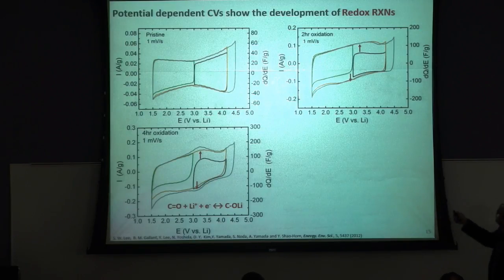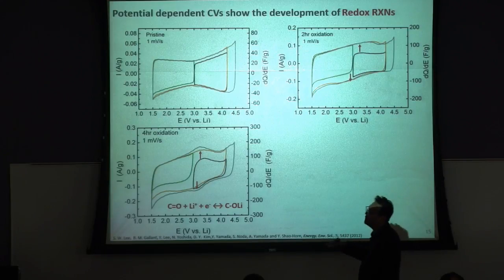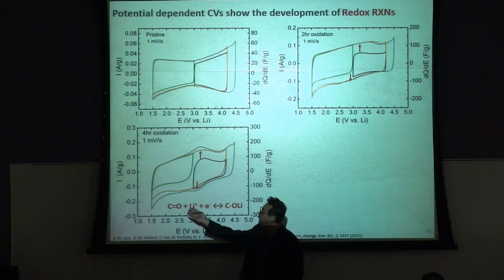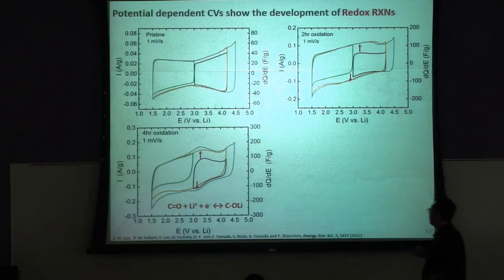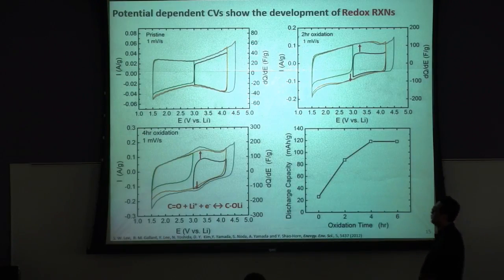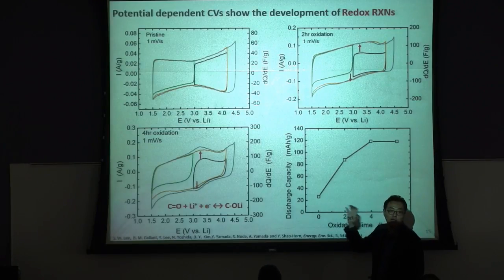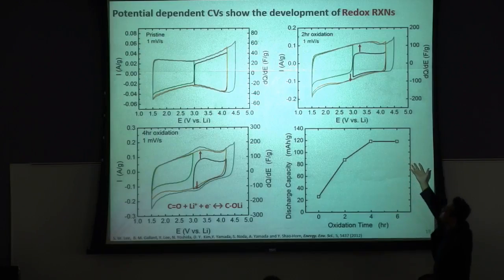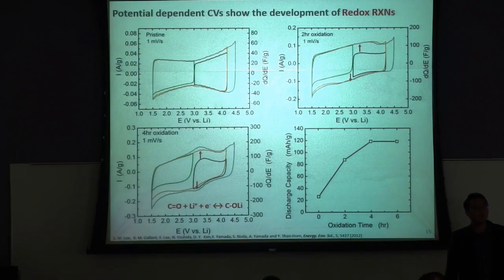Then if we incorporate oxygen functional groups, let's say for 2 hours and 4 hours, we can see gradual development of oxidation and reduction peaks, right? Oxidation-reduction peaks mean a Faradaic reaction, a charge storage reaction mediating some electron transfer. We can expect a redox reaction between the introduced carbonyl group and the lithium ion. If we calculate the capacity, pristine carbon nanotube shows a capacity around 30 milliampere-hours per gram, pure double layer capacitance. But by incorporating more oxygen functional groups, we can increase the capacity up to 120 milliampere-hours per gram. Please remember that conventional inorganic cathode materials have a capacity around 160 to 170. Now we are at 120.